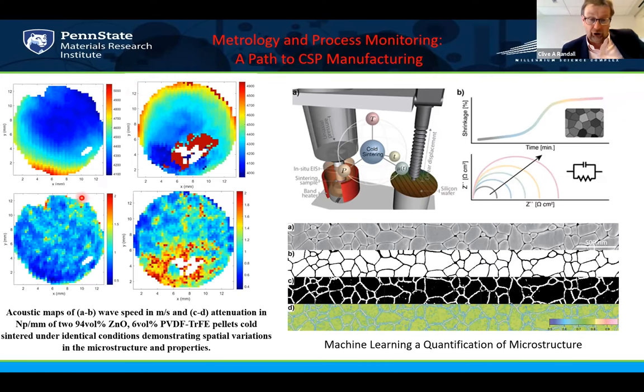We're also using acoustic imaging, which is very powerful, particularly when you're putting polymers in. So we produced six composites that all looked like this. And then we had one that was all about the same density, but not the same properties. And we found with acoustic imaging, you could pick out secondary phases. So we looked both with the velocity of the transmission of the acoustic wave and also the attenuation.